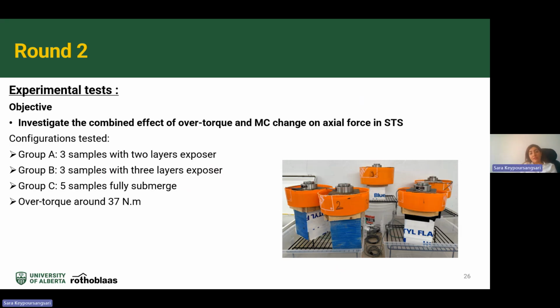Round 2 of the test focuses on the combination effect of the over torque and moisture content change on axial force in self-tapping screws. In this round of the test, we increase the torque until 37 Newton meter. And also our target was finding the effect of different levels of moisture. So we divided our samples into 3 groups.